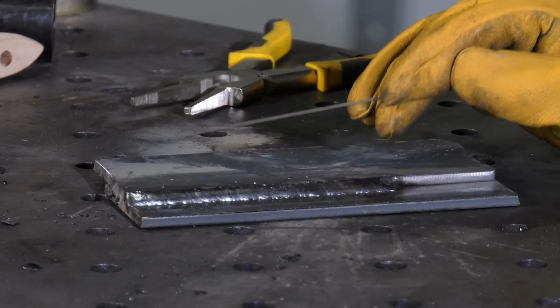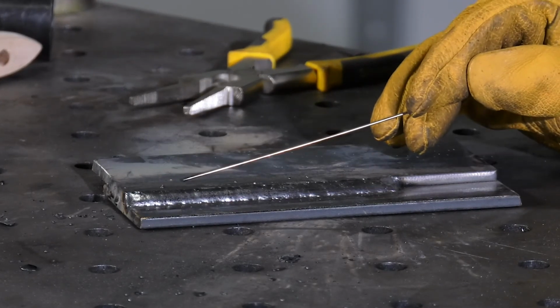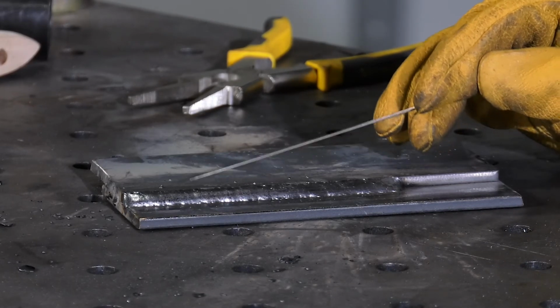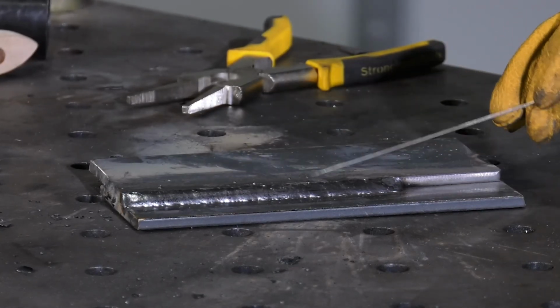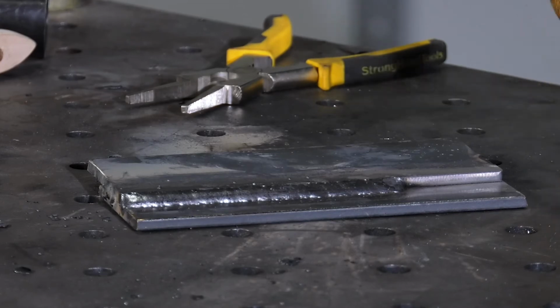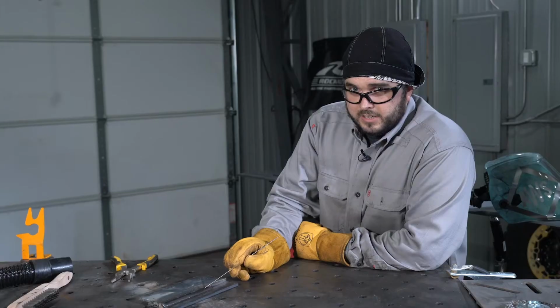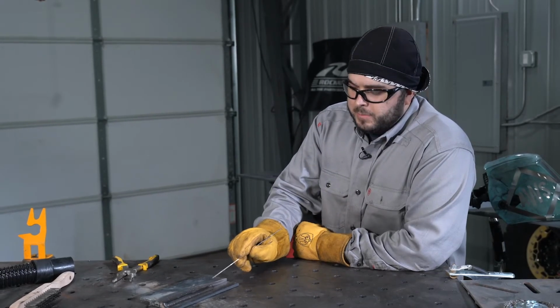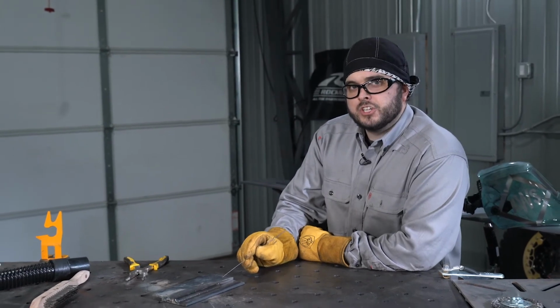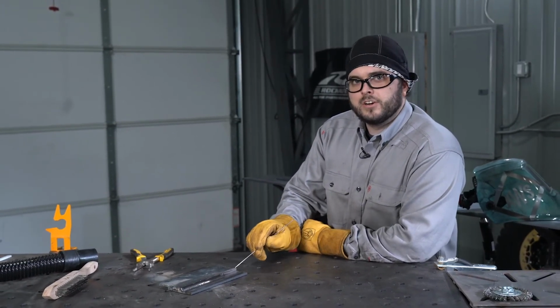We also want to make sure that we got great tie-in from the top plate down to the bottom plate. We don't see any gouges in the base material or undercutting, which is good. This is exactly what we're after. If the weld doesn't quite look like this, you may need to go back to the machine and adjust your parameters to get the weld that you're after.